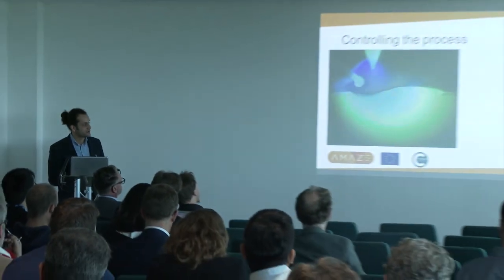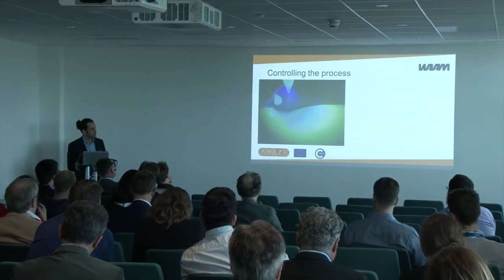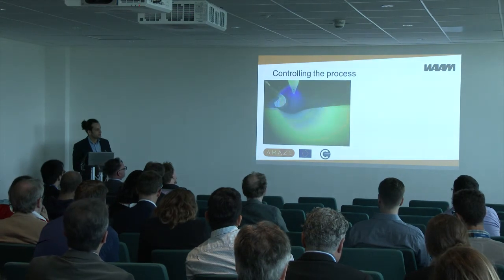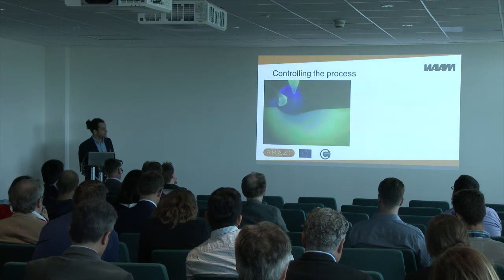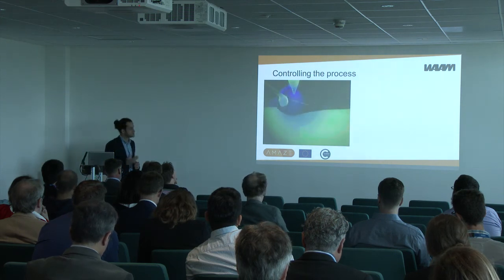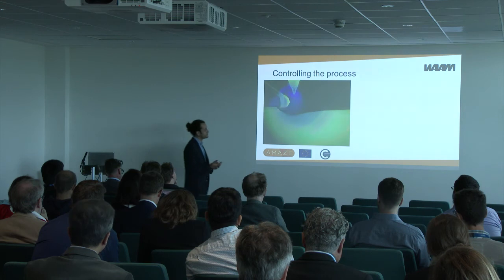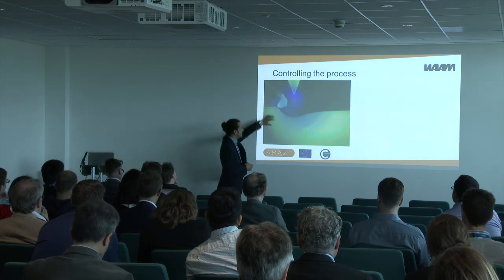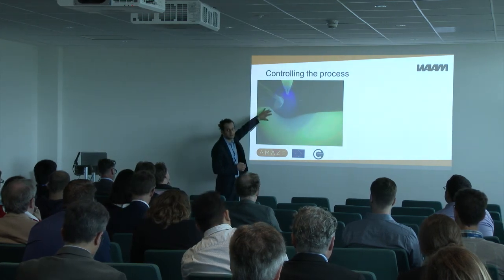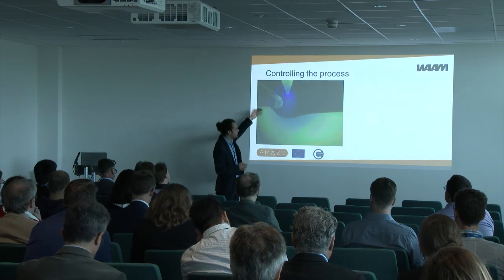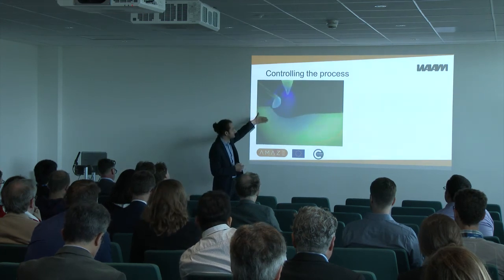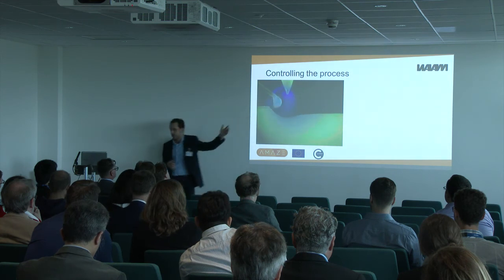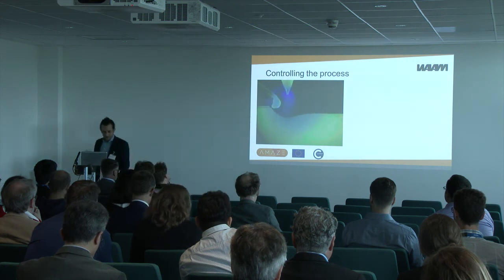Now, the first step, once we were actually able to melt the wire, was to get some stable deposition. And the problem of tungsten is that as the temperature goes up, the thermal conductivity goes down, and the electrical resistivity goes up. And in fact, that's why it's used for light bulbs. The effect of these two is that you effectively are creating an insulating belt around the melt pool. The heat builds up more and more and more, and all of a sudden, instead of building material, we are drilling holes. And that's a little bit defeating the purpose of additive.